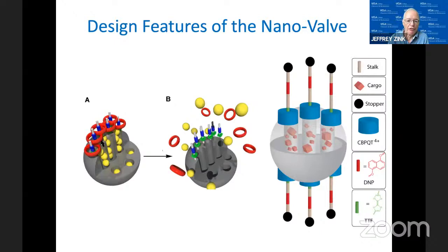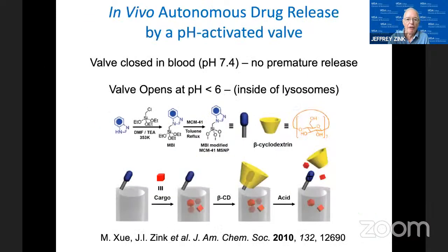The nanovalve consists of a mesoporous silica particle shown in parts A and B there. The pores are illustrated. They're loaded with drugs by soaking the particles in a solution of the drug molecules, the yellow balls. And then these stalks on the surface are attached to cyclic capping molecules. So these are the supramolecular forces that I mentioned briefly. And then under the stimulus, in this case pH, the cap can be stimulated to come off, that opens the pores, and the drug molecule can come out.